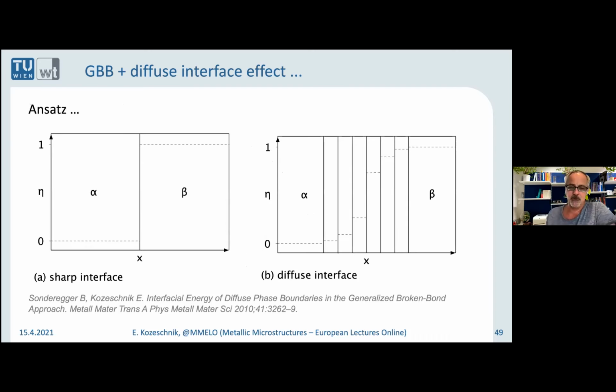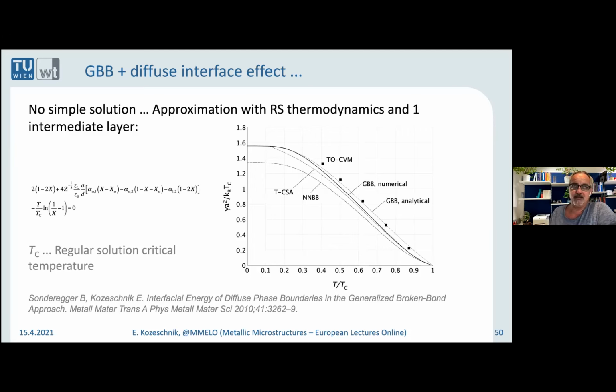So we set up a model for the diffuse interface. We started with a sharp interface, which was more or less this sharp gradient, and then we introduced layers. And within these layers, we could calculate the mixing of atoms. We could calculate some concentration profile in the interface. And from that, we could calculate also the energy change that's related to the interface energy. Unfortunately, the solution is no longer a closed form, but it's an implicit equation. In the most simple case, usually you have to solve the problem numerically.